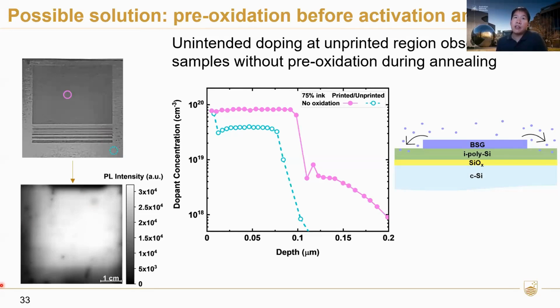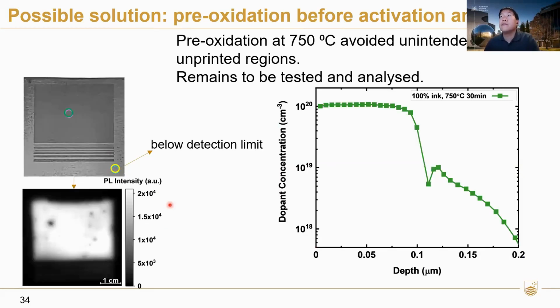And you can see in the PL image too, remembering that when you have doping, it tends to improve the passivation quality of this oxide polysilicon stack, and we get this really blurry image because there's doping everywhere. But if we add a short 750 degrees in situ oxidation just before the 950 degrees nitrogen anneal, we can avoid the unintended doping in the unprinted regions.